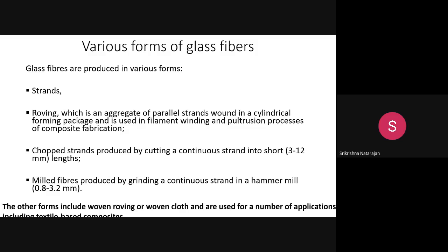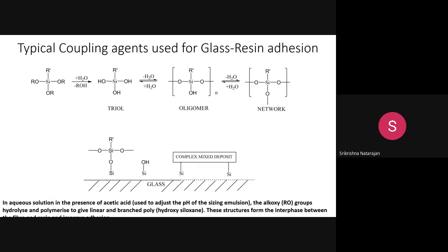You can use it in the form of a continuous strand, a roving, a chopped strand, or a milled fiber. Milled fiber is where you crush the glass fiber into small pieces, where the size gets reduced to 0.8 to 3.2 millimeter by using any kind of milling, like hammer milling or ball milling, so that you can crush them. All these are used in composites. Okay, these are the various forms of glass fibers in which it is sold. So that you need to understand.